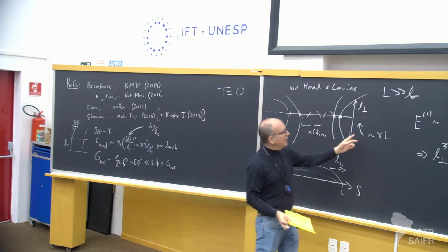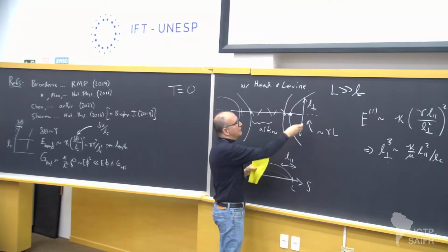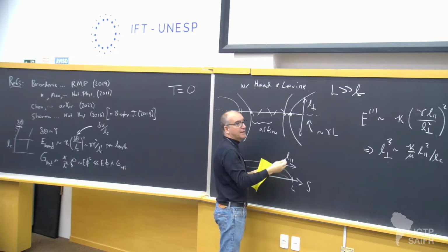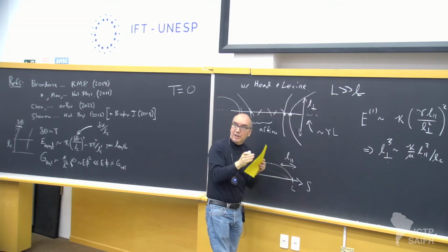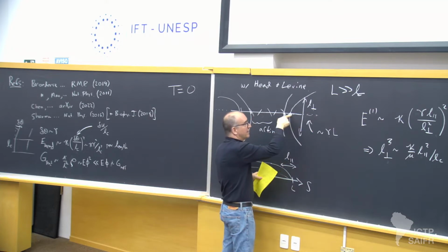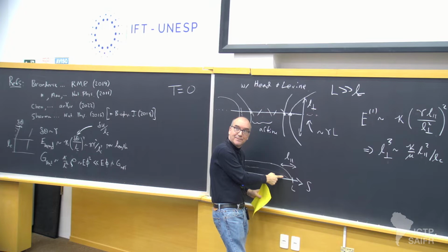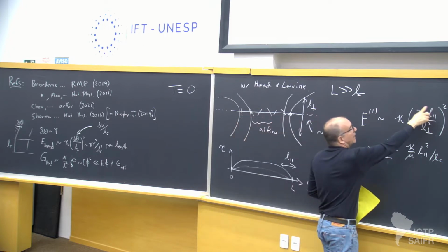And the point here, again, is this. So the transverse displacement of this cross-link, therefore generating a bend here, is not gamma times the distance between fibers. It's gamma times these potentially big distance over which the contraction occurs. That's why I have that combination.